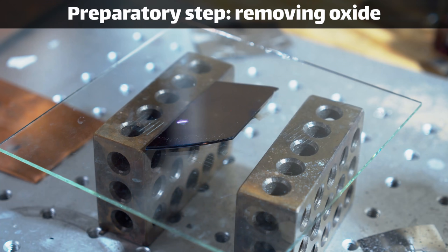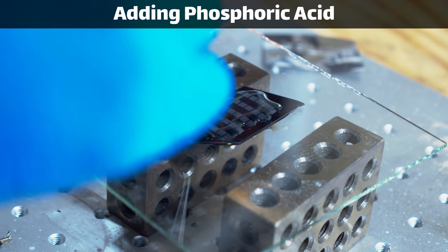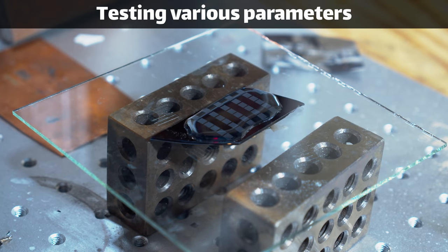Fundamentally laser doping is a thermal process, it's just getting the thermal heat input from the laser rather than from a furnace. You have some type of dopant precursor, phosphoric acid or boric acid, and you can coat the wafer with a solid film or in my case I use just liquid phosphoric acid right on top of the wafer.